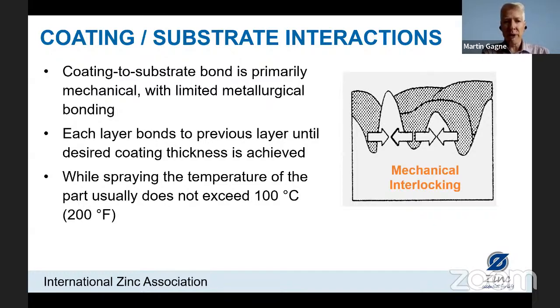And it is called thermal spraying, but it is actually a cold process. There is very little temperature that is passed on to the steel, so there can be no impact on mechanical properties of the steel. There's no possibility for distortion or warping because of heat on one side of a component and not on the other. We've actually sprayed business cards when people come for visiting at a conference, for example, so there's no risk of having the paper catch fire because there's very little temperature transfer during thermal spraying.